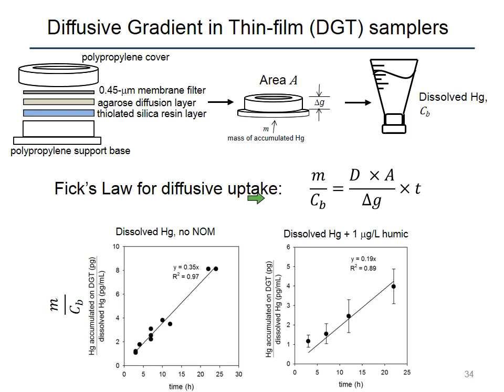And so this is what this equation is: the accumulated mass of mercury divided by the dissolved concentration in bulk pore water is equal to a diffusion coefficient D, as well as a factor correcting for the geometry of the sampler, and then multiplied by time. So if you can quantify the mass of mercury on a sampler and you know the diffusion coefficient, you can calculate the dissolved concentration in bulk pore water. So that's how these samplers are used.